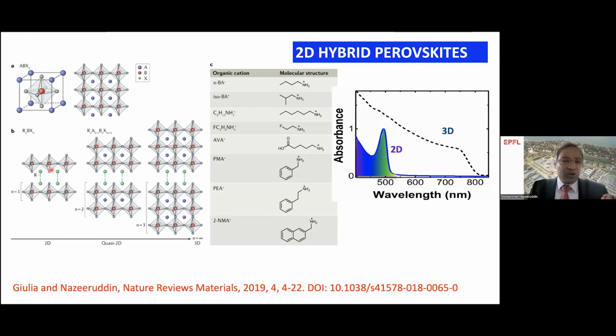Here is what we call the n equals 1 layer. Here we have 2 layers together, separated by the 2-dimensional perovskite. Here we have 3 layers together, separated by the 2-dimensional perovskite. So what are the 2-dimensional perovskite cations? In the middle, I have highlighted some of the two-dimensional perovskite cations, which are organic chemistry, but I will not discuss all these cations. I take one example, phenylethylamine.